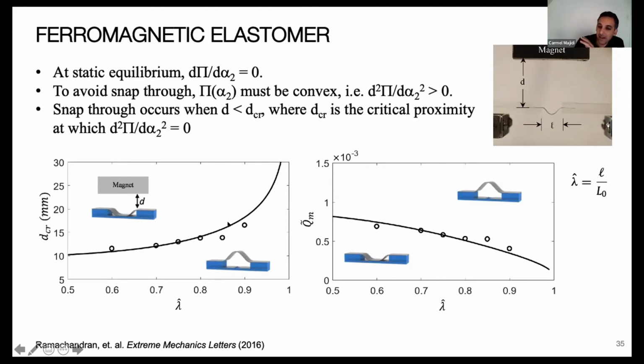And here, without any data fitting, we actually find that these predictions from thermodynamics and these energy principles are in fairly good agreement with what we measure experimentally for snap-through instabilities, for what that critical proximity is of the magnet, at which point we see it pop into this other configuration. And what we're plotting here is what that critical distance of the magnet is as a function of just some geometric features of the initial amplitude of the buckled strip of rubber.